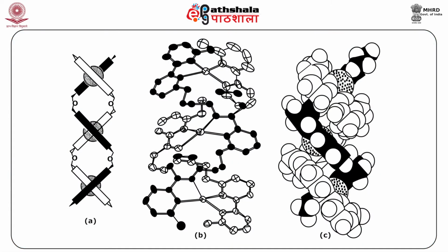Only metal ions presenting the appropriate coordination features with the bipyridine complex will form double helicates. This is also shown to be the case for silver(I), which yields the tri-, tetra- and pentahelicates, as confirmed by determination of the crystal structure of the silver trihelicate. Now, this can be seen here in the next figure.